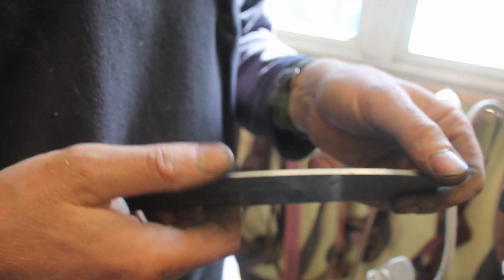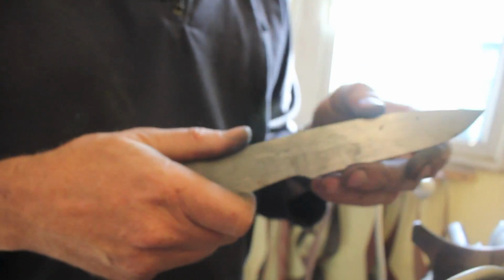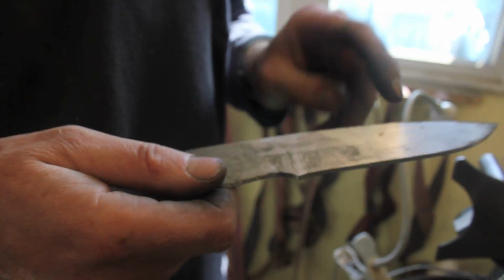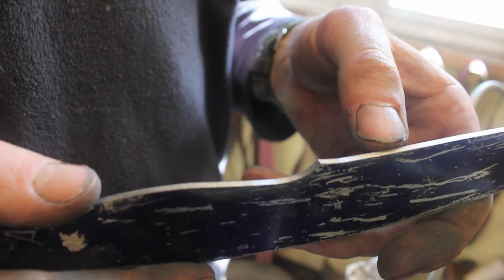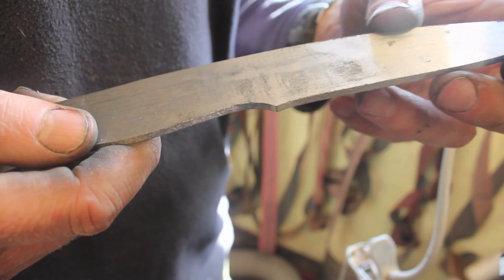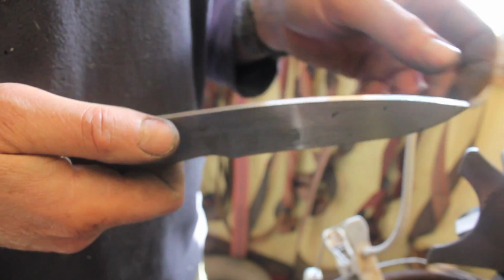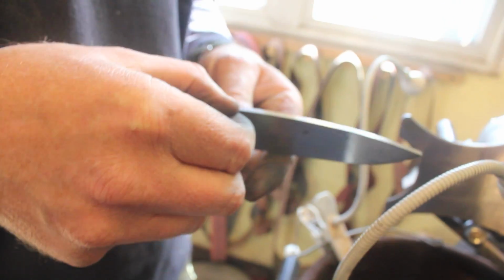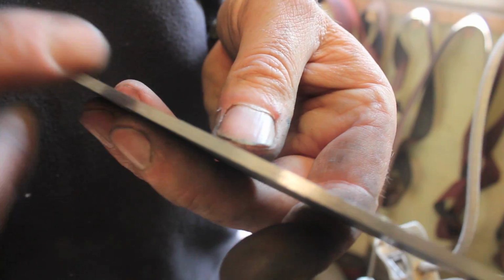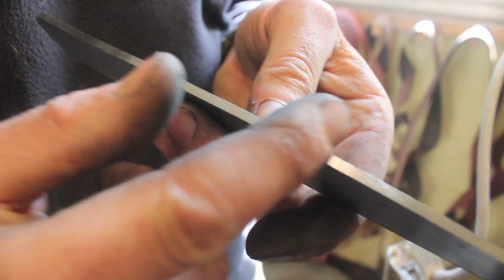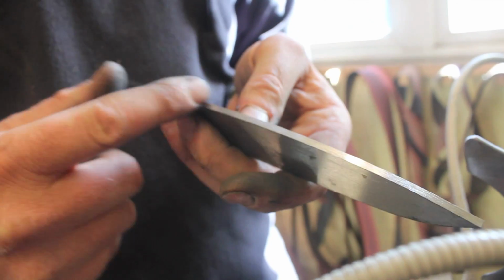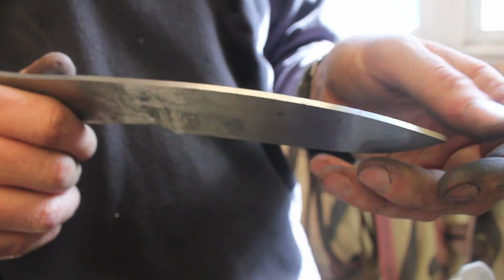I take my knife pre-heat treat to 120 grit finish all round, maybe a higher finish on the flats. And then after heat treat, obviously we're going to go down to finer grits. So that's a 120 grit, and you can see the lines in there. Eventually I'll be going down to much finer grits, with a progression of grits, until that comes almost to a polish. Okay, gotcha.